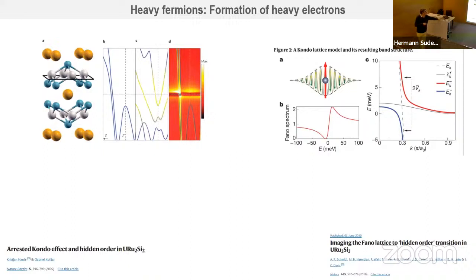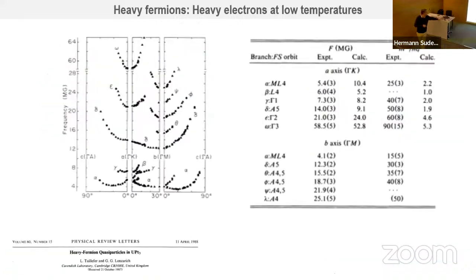And when you take a look at the band structure, so for example, here, the F band structure, you can actually reproduce quite well what is obtained in the experiments, particularly here close to the Fermi level. And when you consider the electron weight outside the Fermi level, you see that there is lots of weight close to it, but at finite energy. So these things can be described more or less, and of course the question is how to describe this more precisely. But there is one simplifying situation which comes from this experiment.